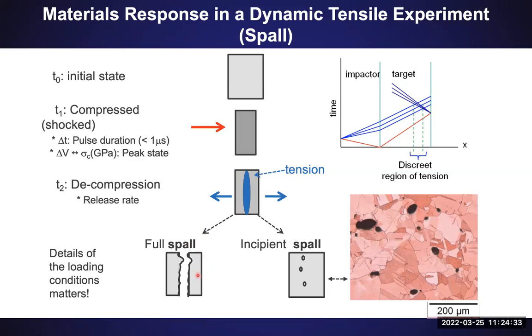And that's not as interesting to us as material scientists. What we tend to focus on is the other thing that can happen, where you can be very careful about your loading conditions and induce very early stages of damage, where voids are just starting to form in your microstructure. So you can understand where voids nucleate and why they nucleate in a certain way, because when you're designing materials, you're trying to avoid that. So here is a micrograph of, I think this is copper, showing voids nucleating at different grain boundaries in copper.